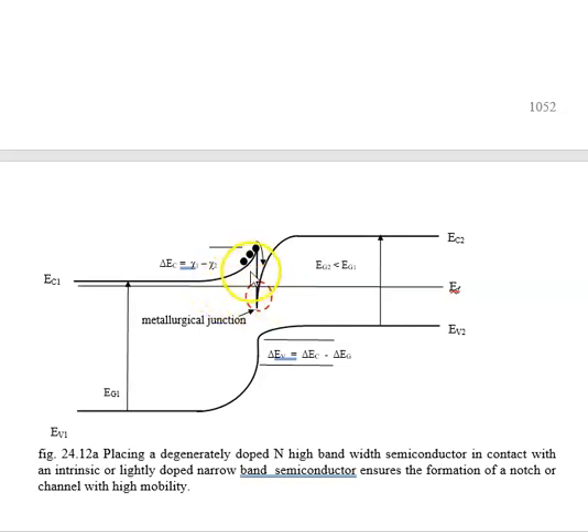When we put these two together, we have a high Fermi level and a low Fermi level. The Fermi levels equilibrate because it's in equilibrium, and electrons are transferred from semiconductor material 1 into semiconductor material 2, and they basically swarm into the notch. So here's the notch. It is in semiconductor number 2, the intrinsic one, and that's the key, the intrinsic doping, essentially undoped. So it's got high mobility, it's got a nice channel, and that is a really, really good situation. So all these electrons and lots more jump into what we call a quantum well, and it's a quantum well because this distance here is incredibly small, on the order of at most a few tens of nanometers. So that's the HEMT. That's it.